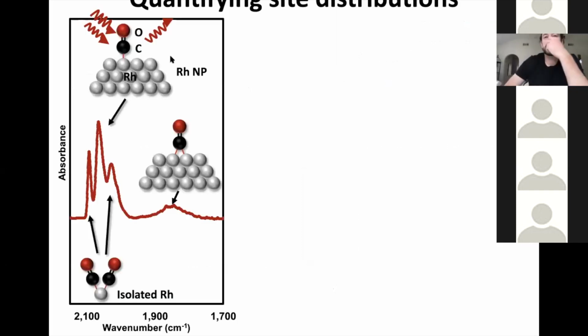We used CO probe-molecule infrared spectroscopy. This was the most developed approach for studying dispersed rhodium species on oxides and trying to differentiate single atoms from clusters. So if I take, say, 2% rhodium on TiO2, and that's what this spectra is for here,